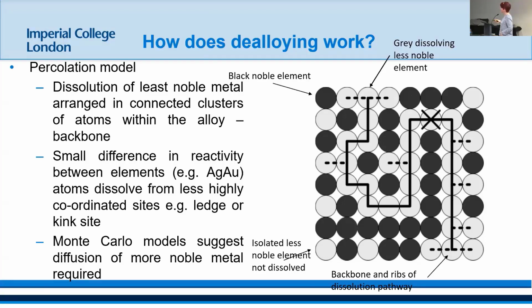You also need a little bit of movement from the other elements. So in the gold silver case, the gold diffuses and allows this process to happen. So it's this competition between dissolution tendency and surface diffusion that enables you to get the dealloying threshold. And there's lots of work done by other groups, particularly with Monte Carlo simulation, that predict some of these behaviors.